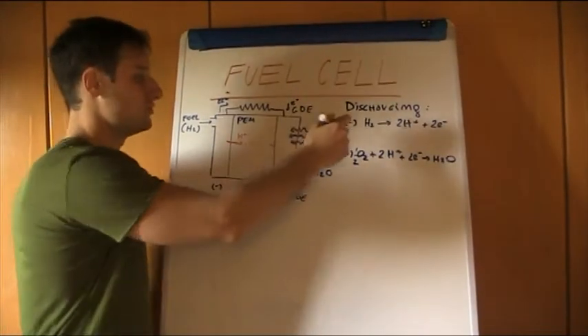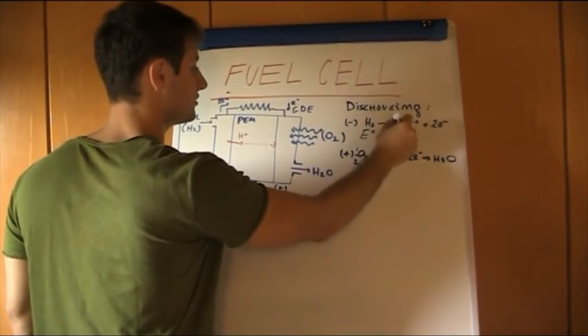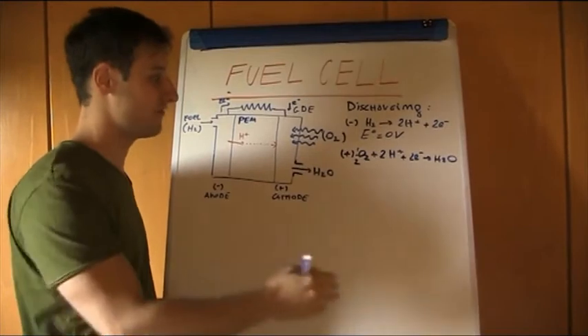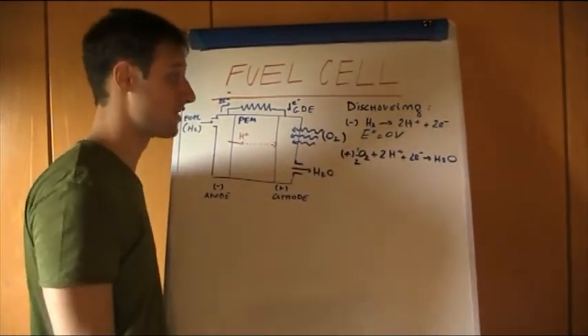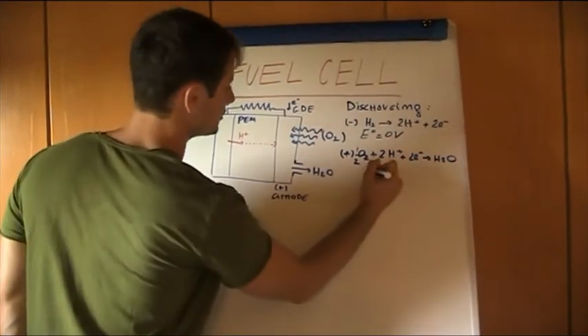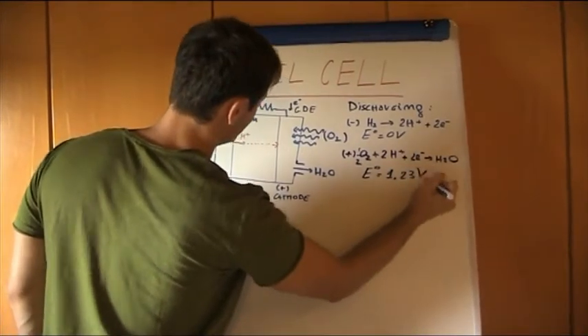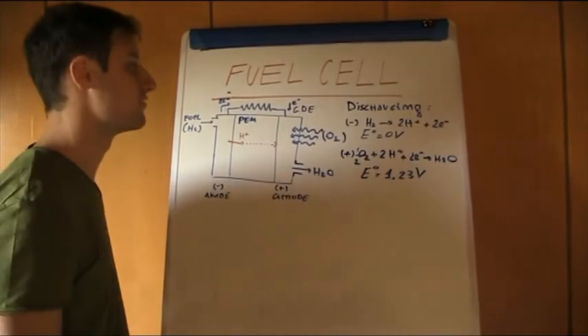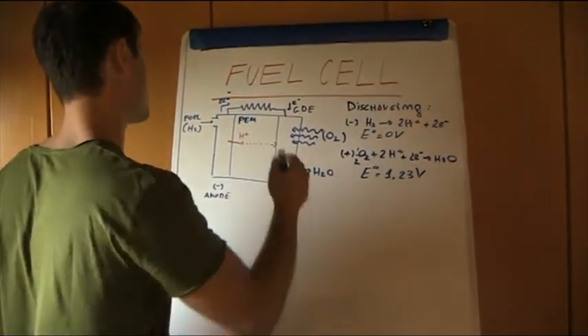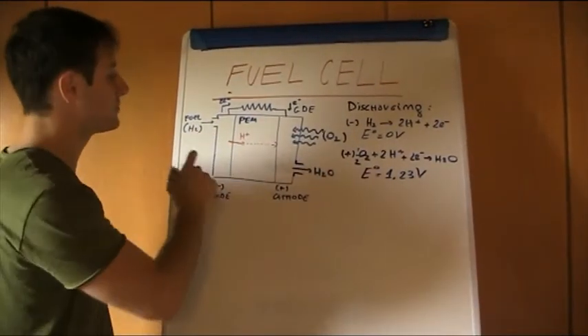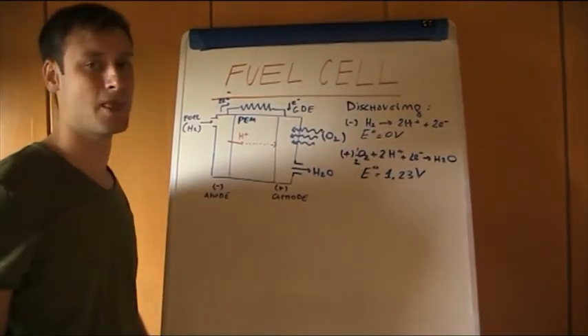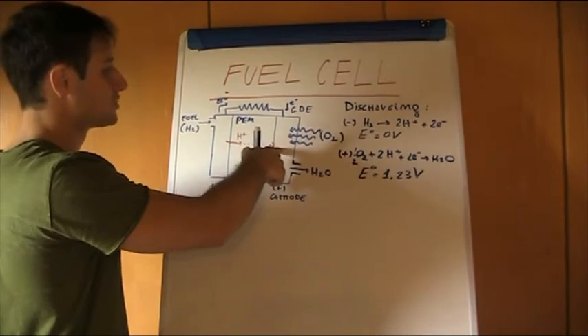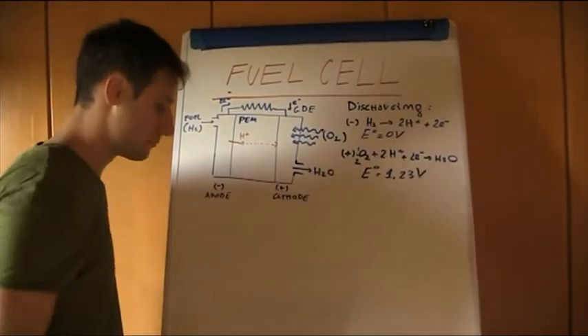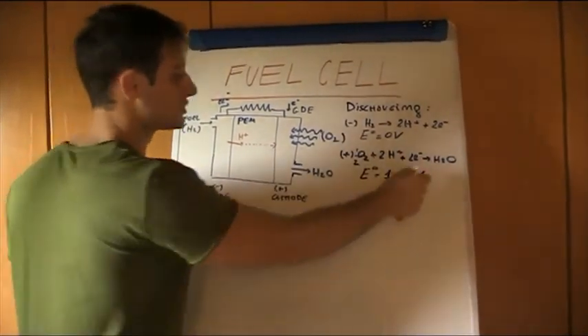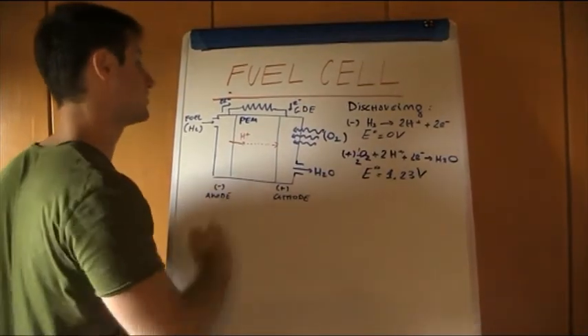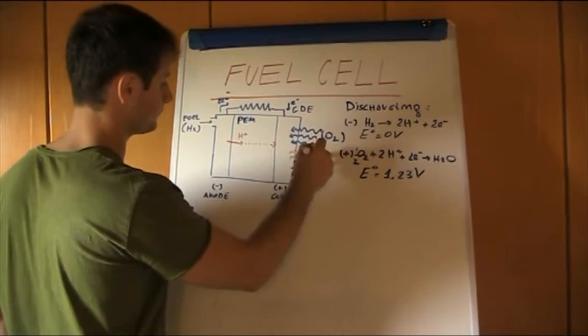Obviously, this potential in standard condition is equal to 0 volts, since this is the same reaction as hydrogen reduction, even if it is proceeding toward an oxidation, because we are involving the same redox couple. And also in this case, we have 1.23 V in standard condition. So basically we can see how the difference is equal to the difference of the water line, and we can say that a fuel cell based on hydrogen as fuel represents a process that is the opposite of, for instance, water electrolysis. And since we have the formation of water due to the interaction of these molecules, this is an exothermic reaction, since we are creating one molecule starting from more species, and so we have a little bit of heat release. It should be tuned and managed.